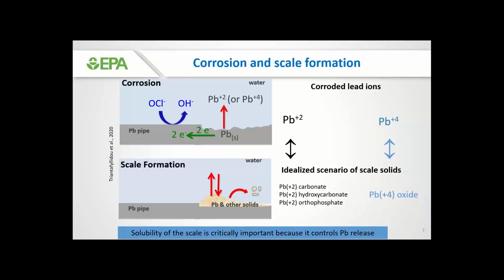The most important part is actually scale formation, which is depicted at the bottom schematic, where those ions that were previously released through the process of corrosion react with other constituents in the water to form a scale. For example, if we have lead +2 ions leached out in an idealized scenario of scale solids, this would react with the carbonate system in the water to form either lead +2 carbonates or lead +2 hydroxycarbonates. If we were adding an orthophosphate corrosion inhibitor into the water, in the ideal scenario, we would be forming a lead +2 orthophosphate scale. In the case where we have really strong oxidizing conditions and lead +4 ions being leached into the water instead of lead +2, in this case we would have lead +4 corrosion solids forming